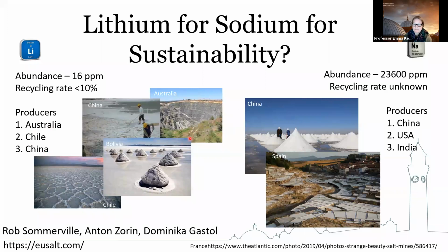Australia is mainly from rock, such as spodumene, and China, Bolivia, and Chile have large salt plains which you can mine the lithium from. So essentially they dissolve up the lithium chloride that's beneath the ground and bring it back up to the ground and then evaporate the water off, and you end up with these little piles of salts that can then be transformed into other materials.